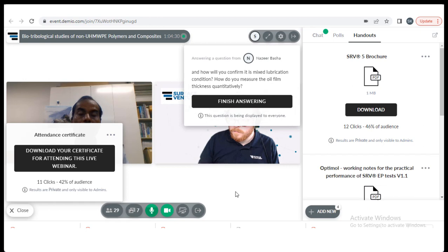Yeah, so I have already answered how you confirm the mixed lubrication. But how do you measure the oil film thickness? That is a big problem. And as you know, in mixed lubrication, it is not a uniform film thickness. So that's another big problem. But if you have, for example, a hydrodynamic condition where you have got a throughout film formation, then you can use the optical method to measure the film thickness. But in a mixed lubrication, it is perhaps extremely difficult to measure experimentally.